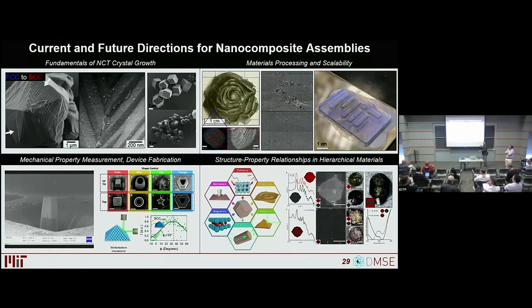So the vertices are more reactive than faces. They grow from the vertices, but the vertices don't necessarily correlate to the unit cell dimension. So for example, in that FCC case where we had 12 different points, that's a 6-fold symmetry. You can't get a 6-fold symmetry out of a cubic unit cell growing along the 100 or 110 or 111 types of directions. That is not something you would predict based on that. So it's not a complete departure from what you're talking about, but when we think about these things as a diffusion limited process with very large, fuzzy building blocks, we can't necessarily correlate that the structures you would get from a nanoparticle are going to be exactly the ones that we would get. And so we need to put a little bit more time into thinking about what exactly is that difference and how does it define what we can and cannot make? Okay, great.